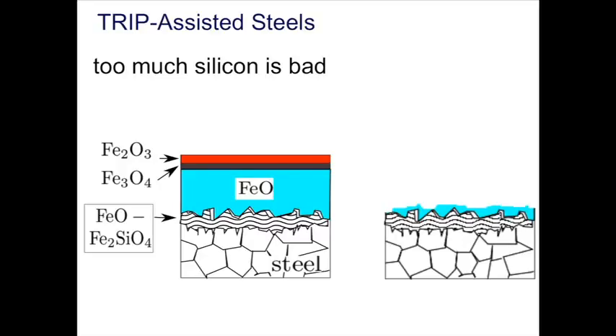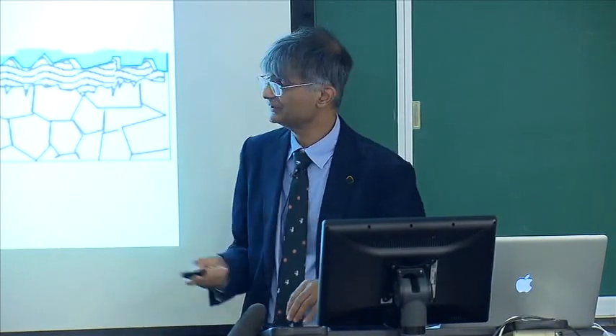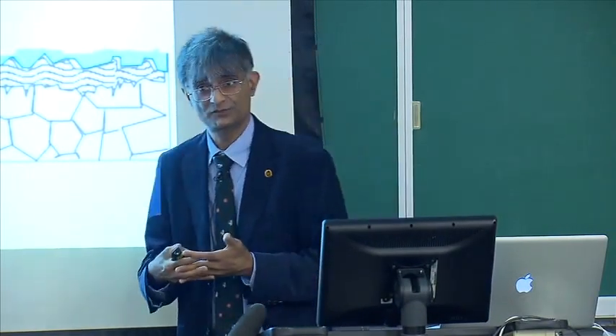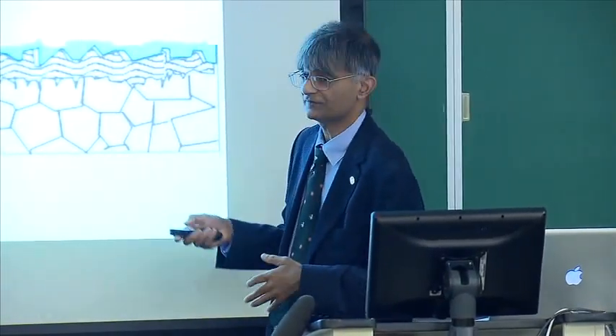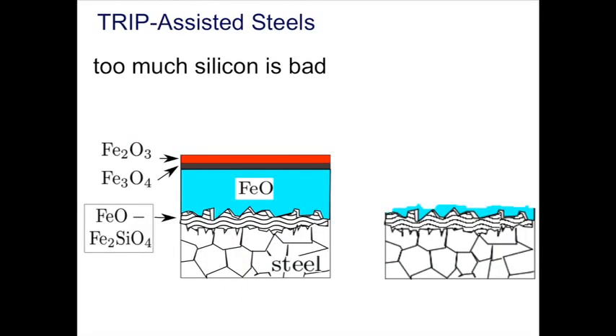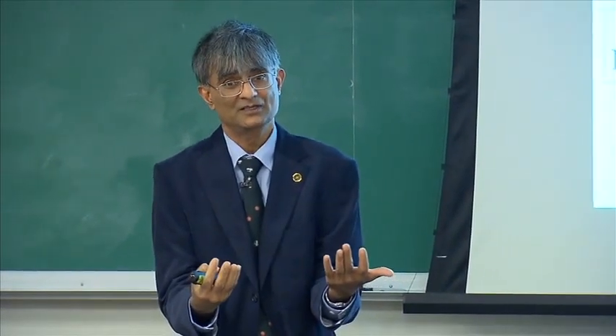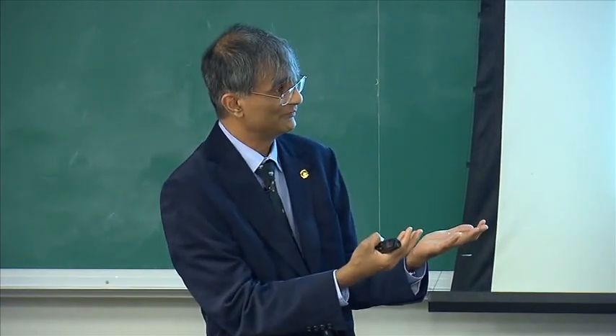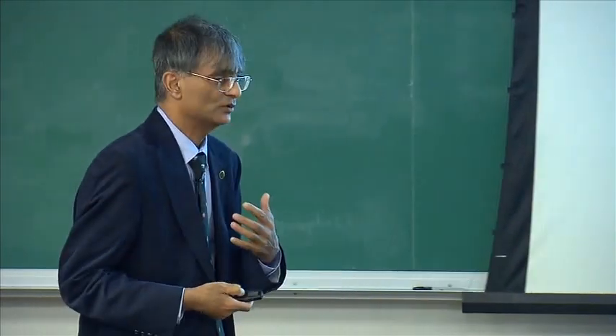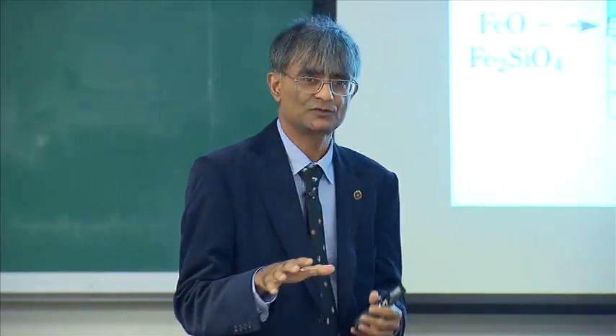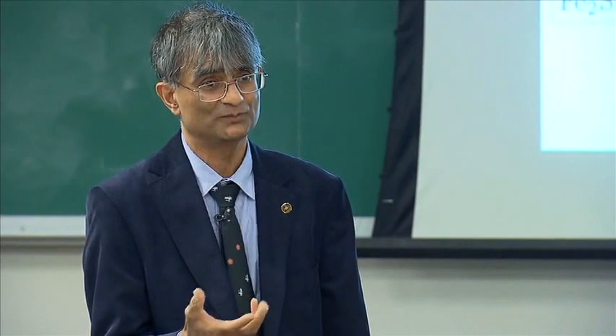But as your wonderful student pointed out, there's a problem, that silicon forms an oxide during the processing, which is called fayalite, here, Fe2SiO4. And that can be liquid at your heat treatment temperature, so it penetrates the steel and locks itself to the steel. So when you come to remove the oxide by the processes that I have in the steel industry, you are left with some remnants of this iron oxide because it keys with the fayalite. And that iron oxide then oxidizes to a red colored oxide, which is unacceptable just from looking at the steel. But it's even more unacceptable when you go to coat it with zinc because it doesn't wet at those points. So we don't really want any blotches on the surface, external surfaces of a car body. Yeah, you wouldn't buy it.